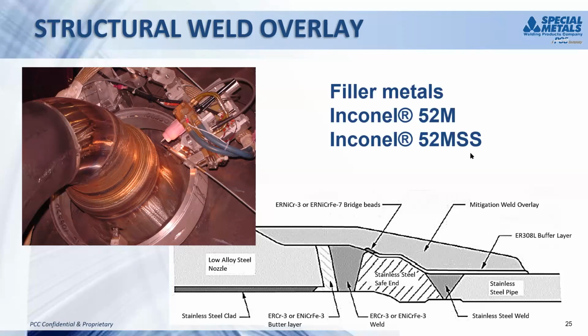One of the simplest ways to mitigate this was to simply cover that entire weld joint with a much more corrosion resistant alloy like an Inconel 52M or 52MSS that basically just covers the entire weld and eliminates that potential problem. Next slide.